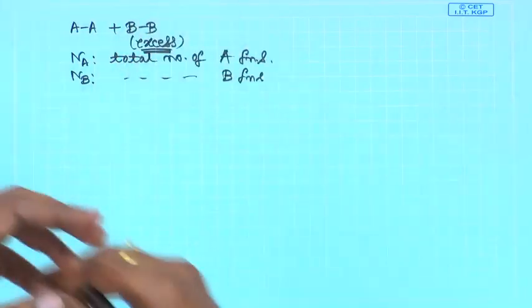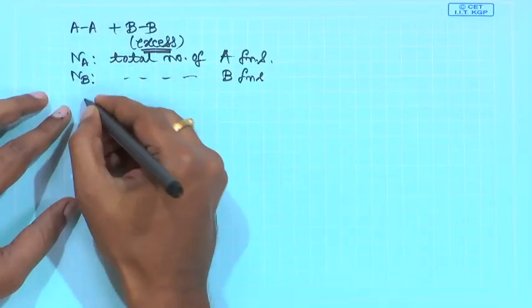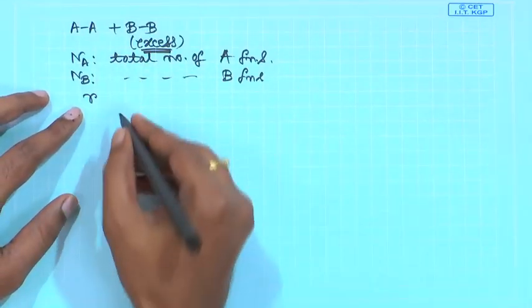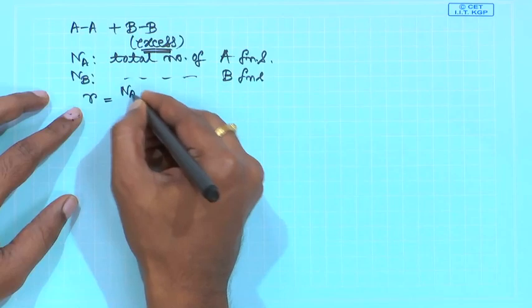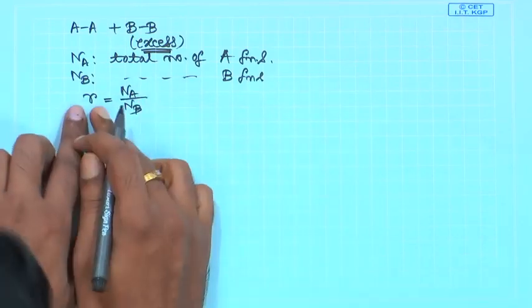So, your stoichiometric imbalance, in fact, you say stoichiometric ratio. So, from ratio the term R comes, the letter small r, this is stoichiometric ratio, that is Na divided by Nb. This ratio is never greater than 1. So, if you have one of the monomers in excess, that comes in the denominator, the monomer which is not in excess, that comes in the numerator.